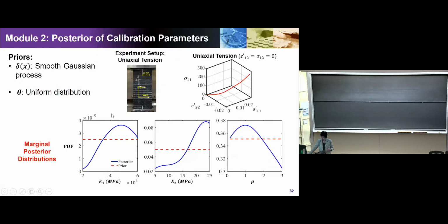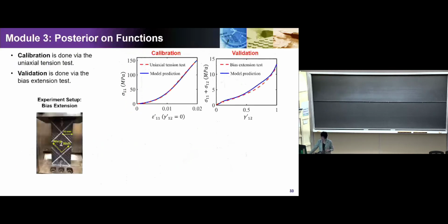Module 2 is to first identify the posterior for the calibration variable, using conditional probability and lots of random simulations. For the prior, we just assign a uniform distribution to the unknown parameters, such as Young's modulus, based on experiments. Then you can see the posterior after taking into account the physical experiments. There is still uncertainty. The data we use is only the uniaxial tension test data, and those quantities are measured for the specimen. This tells us how much uncertainty we have. But in general, they're pretty much identifiable. In some other research, we talk about how to deal with non-identifiability.